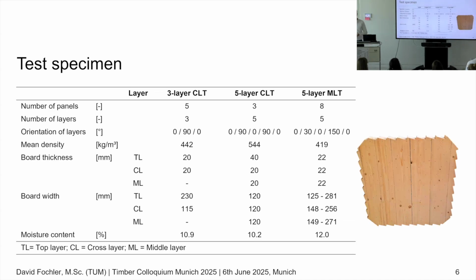So we had to prove our concept by practical testing. And therefore, we used 3 different kinds of specimen. First of all, 5 panels of 3-layer CLT. Then on top of that, we tested 3 panels of 5-layer CLT. And to check the full abilities of the frame and of the notches, we used 8 specimens of mechanically laminated timber. And these even had 2 diagonal-oriented layers. It's here in the table. One had 30 degrees and one had 150 degrees angled to the top layer.